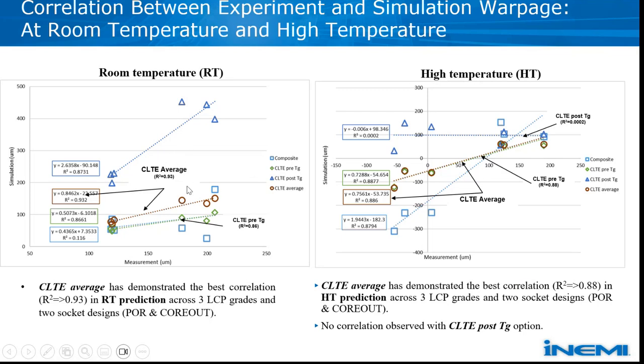For correlation with the Mori-Tanaka model, the CLT pre-TG and CLT post-TG methods record a good correlation of 0.886 and 0.873 respectively. The CLT average method records the best room temperature warpage correlation of 0.932. In general, the CLT post-TG over-predicts the warpage magnitude, meanwhile other methods under-predict it for all three LCP materials investigated in this study. A similar correlation comparison for high-temperature warpage prediction is shown in the right plot.